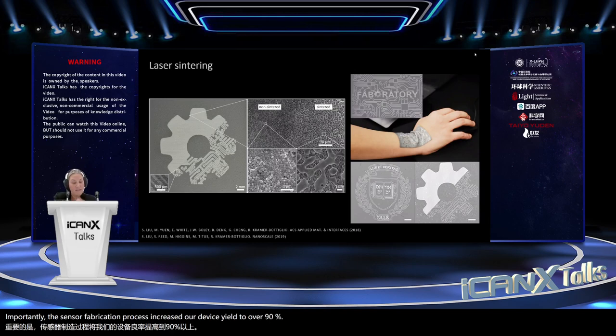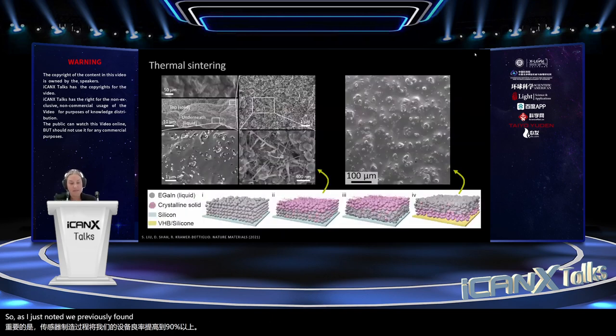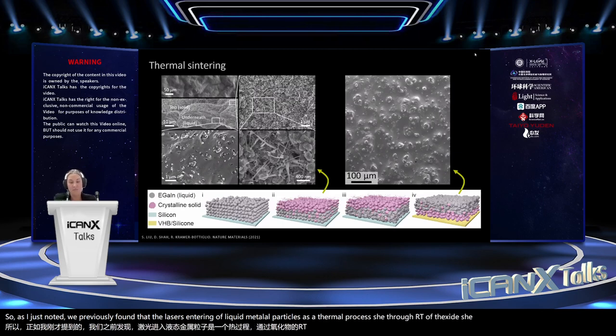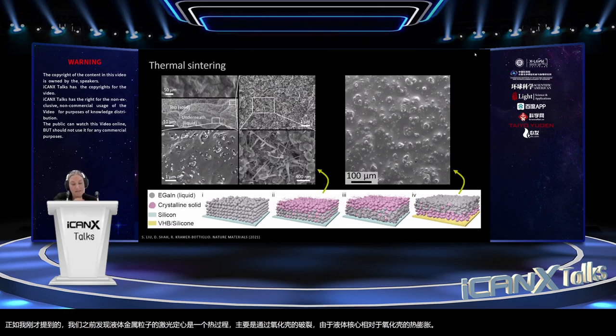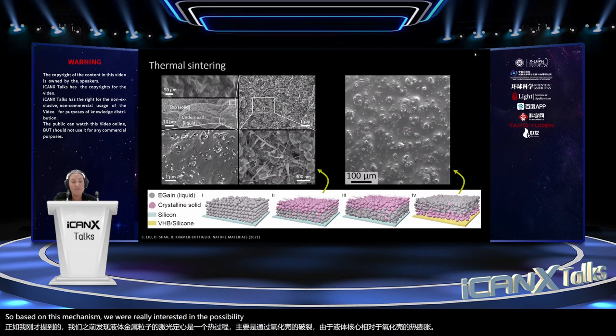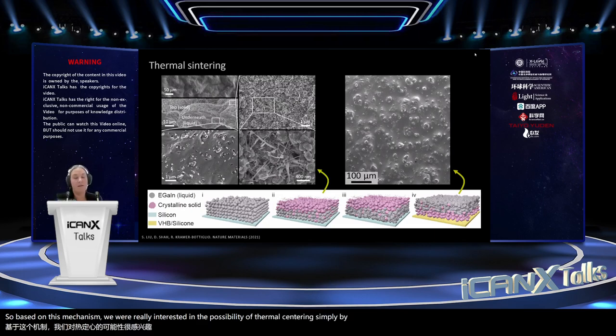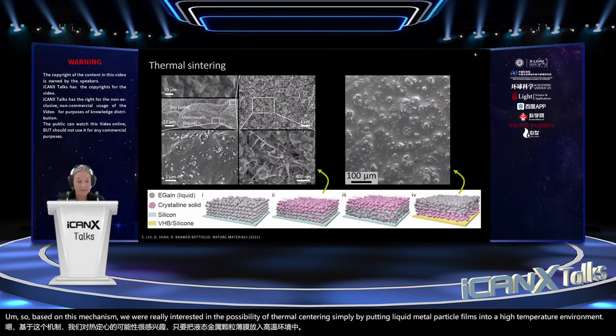So as I just noted, we previously found that the laser sintering of liquid metal particles is a thermal process achieved through rupture of the oxide shells due to the thermal expansion of the liquid cores relative to those oxide shells. So based on this mechanism, we were really interested in the possibility of thermal sintering simply by putting liquid metal particle films into a high temperature environment. And this is what we found.